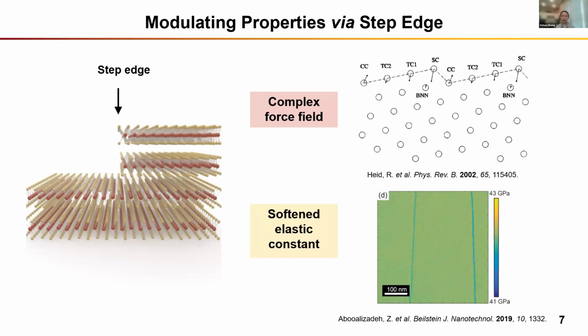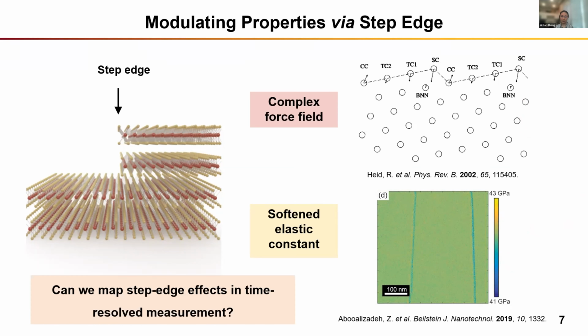To build upon this observation, we started to explore more into potentially utilizing step edges to modulate properties. So first principles studies tell us that the atoms sitting at the edge experience a different force field compared to the bulk atoms. So their lowest energy states or relaxation states are different from the bulk atoms. And this can result in a modified bond length between the edge atoms and their nearest neighbors as compared to the bulk bond length. And this ultimately manifests as new electronic, mechanical, and vibrational properties. So for example, increased friction and reduced elastic constant have been reported near these edges. So this leads to the question of, can we use the unique capability of UEM to really map out the properties modulated by the step edge?